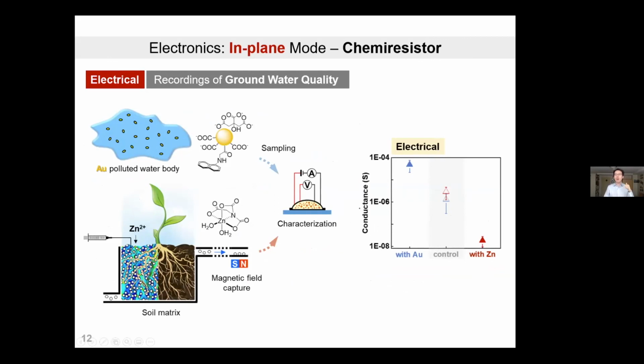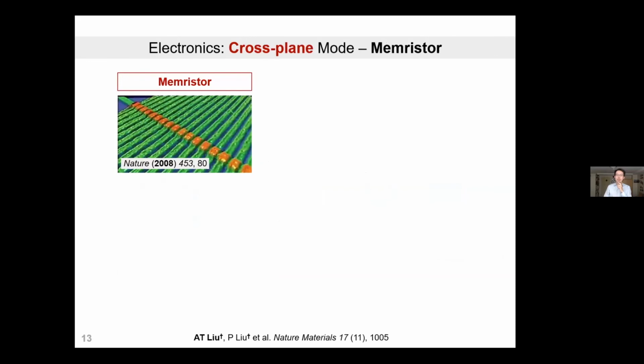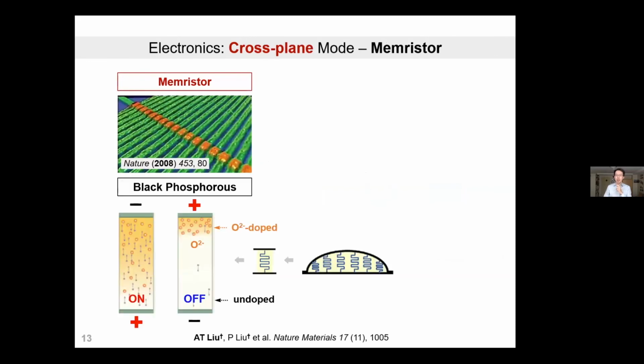I think a more fun part of the geometry of our particles is actually in the cross-plane domain. Imagine you have this particle, let's say you make it with graphene. Then from top to bottom, you basically have this 2-terminal device, where you have a graphene electrode, another layer of graphene, and in the middle you can print whatever you want inside that polymeric gel that you use to make the particle core. In this case, we're making them into a memristive device.